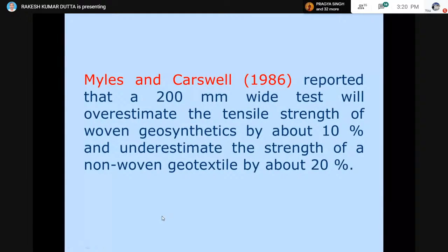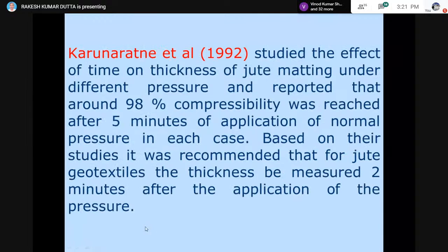Then in the year 1986, the work of these previous two researchers was extended. They took a 200 mm wide specimen and conducted the test using a 200 mm wide test of the polymeric material, and they found that the strength of this wide specimen of the polymeric material gives you a 10% overestimation of the tensile strength in case of woven, and in case of non-woven, it is underestimating the strength by about 20%. So this was another study related to characterization, reported in the year 1986. Then after 86, another study was reported by Karunaratne in 1992.